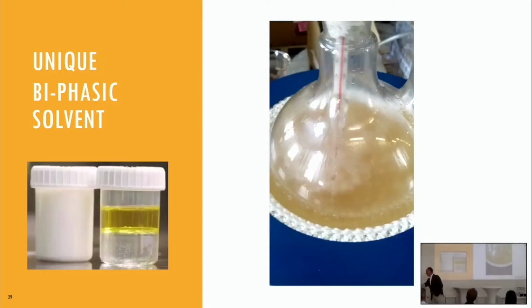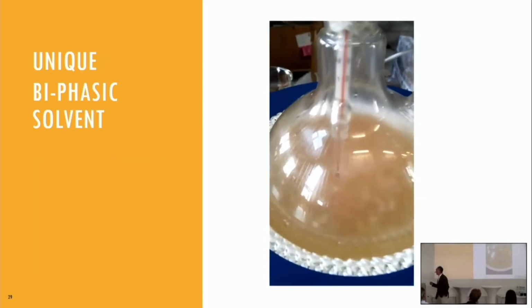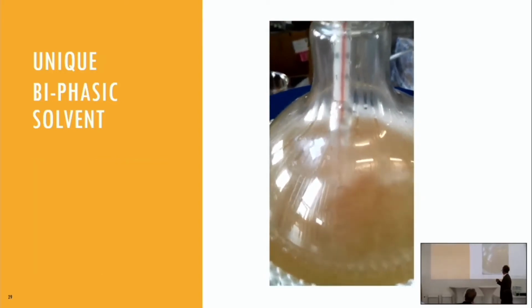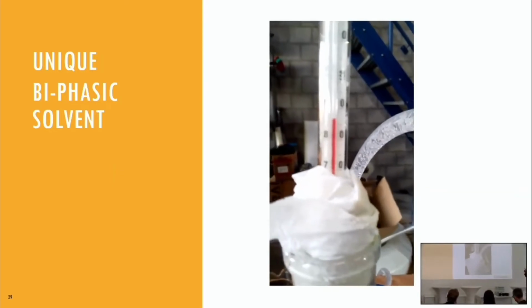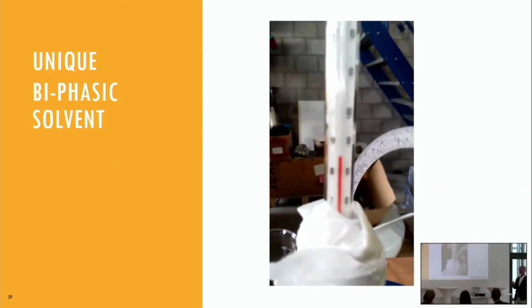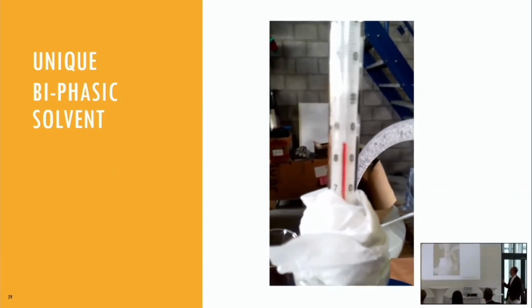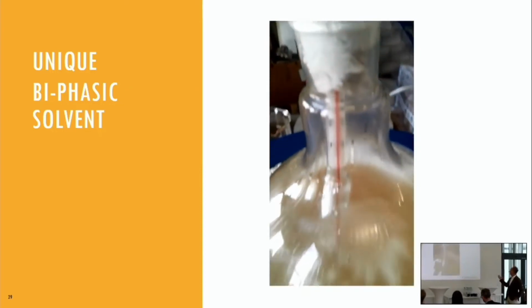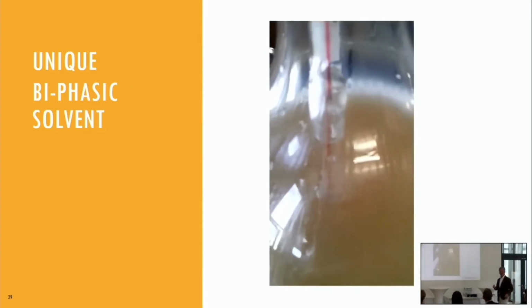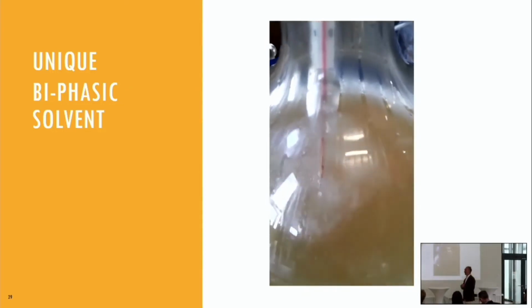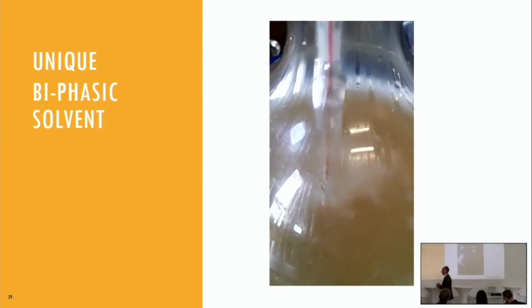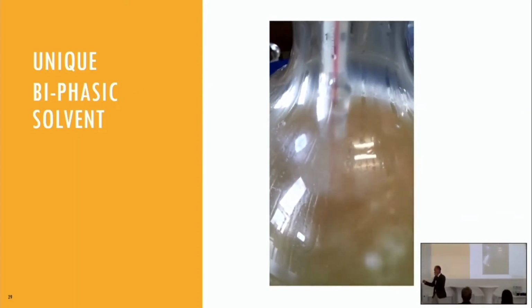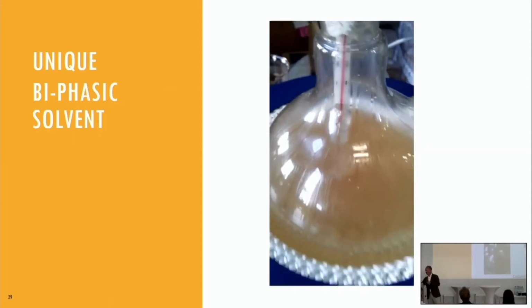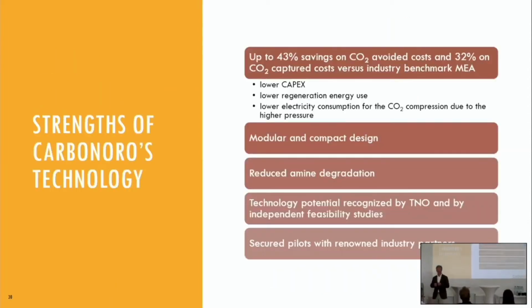And you can see that on this small video that was taken in our lab. Here you see it's operating at 85 degrees, which is a relatively low temperature, and the CO2 is actually bubbling out of the solvent. So operating at low temperature gives an energy advantage over the traditional solvent in the industry, which is called MEA.